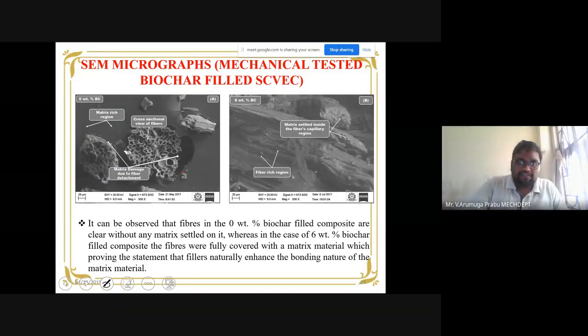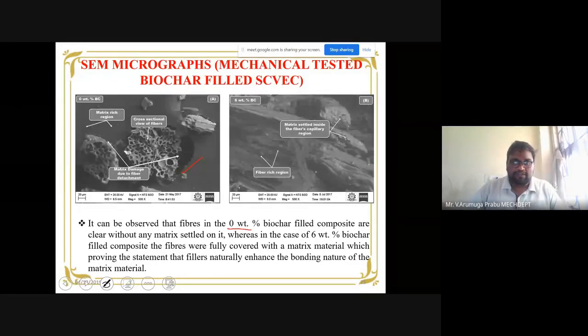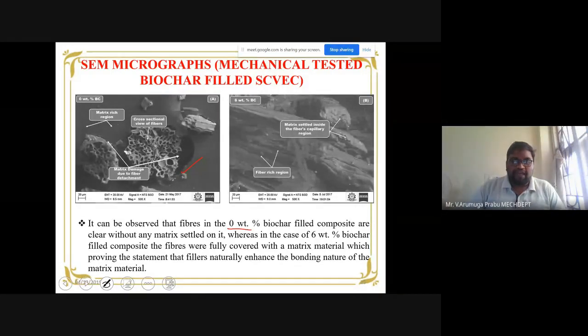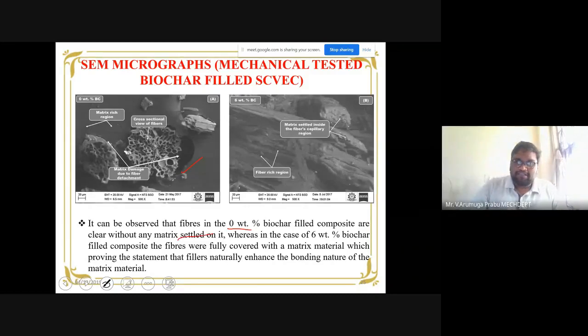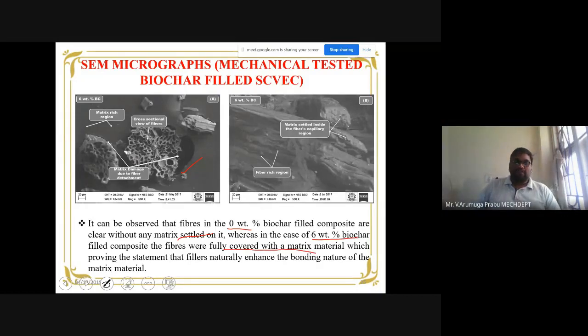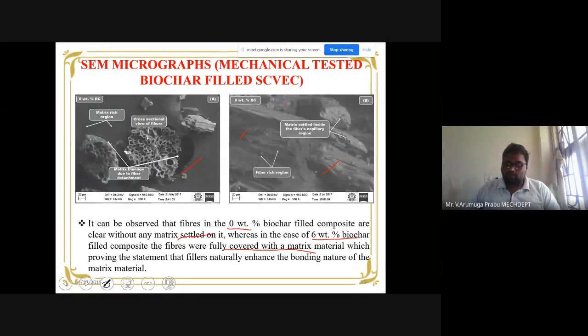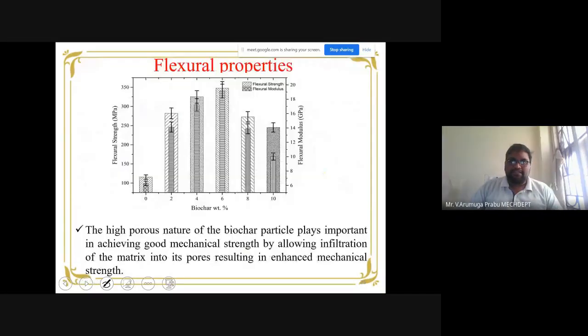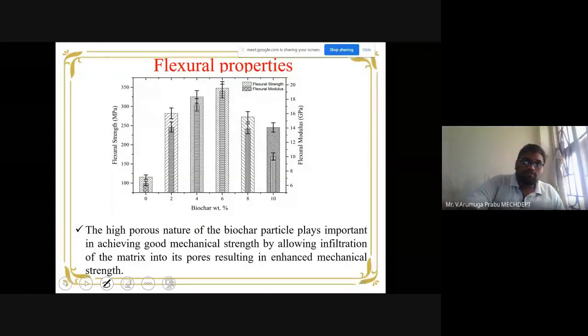The first image shows the 0 weight percentage biochar, where there is no matrix settled, as is evident. On the other hand, with 6 weight percentage biochar, the fibers are fully covered with the matrix material. So the fillers and everything are held strongly here, which gives a good bonding nature. Because of the good bonding, ultimately the strength gets improved a lot. That's the reason. Then in the flexural also, the same thing.